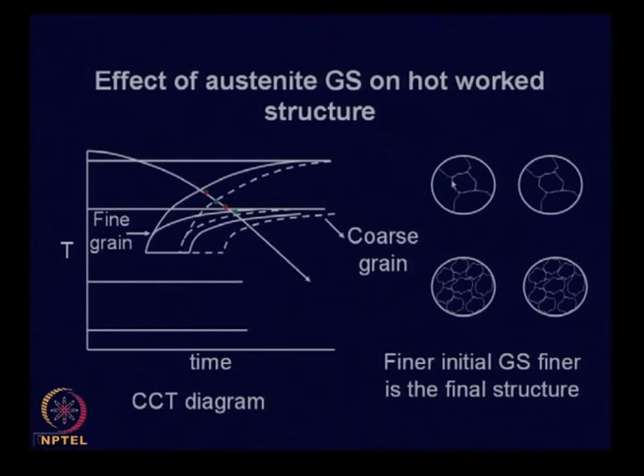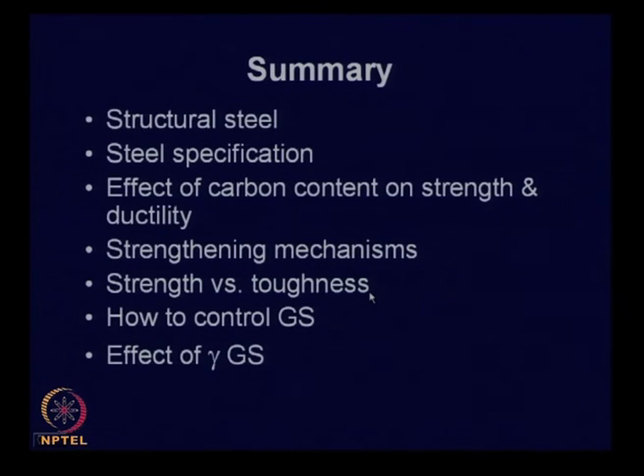Initial grain size, if it is coarse, and if you deform it, the final structure is likely to be coarse. If the initial austenite grain size is finer, and you deform it further, you make it more fine, and the chance of getting a fine grain is higher. And we also know that austenite grain size does affect the CCT diagram, which is pictorially shown here. So, in this case if the grain size is fine, the transformation starts at a higher temperature. If grain size is coarse, transformation will take place at a little lower temperature. So, by playing with this, it is possible to control the final structure of steel.